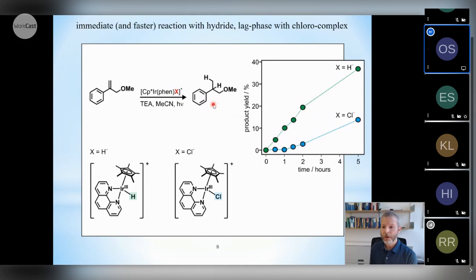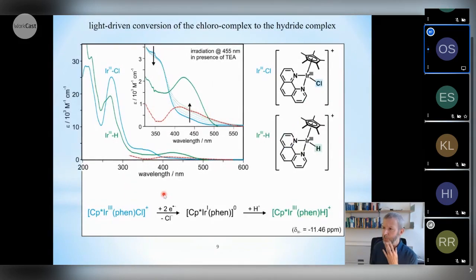However, when using the hydride complex here as a starting material or as a catalyst from the very beginning, there is immediate product formation, suggesting that over time, when irradiating this chloro compound in the presence of excess triethylamine, it actually converts to the iridium(III) hydride complex, and this is then the actual true catalytically active species. And this is supported by time-dependent UV-Vis absorption and proton NMR experiments.